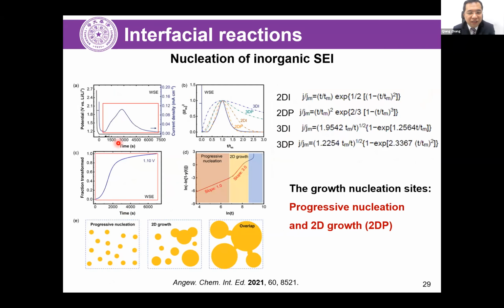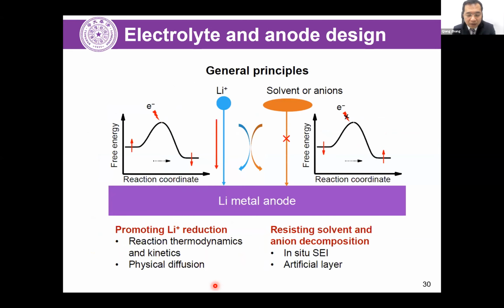And then we try to fit the evolution and the growth behavior of the inorganic SEI. It is found that at the beginning the slope is 1, but then it becomes 3, indicating progressive nucleation on the metal at the beginning, and then 2D growth in which the inorganic SEI attaches on the surface, and finally they overlap with each other to get a continuous film to reject the direct contact of these metal anodes with organic electrolytes.